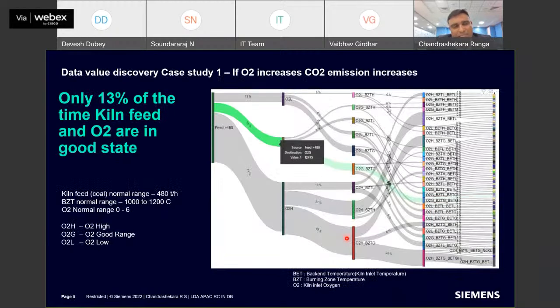When we did the case study, we noticed that only 13% of the time, both kiln feed and oxygen are in good condition. You can see this is called a Sankey plot, where on all other areas, only 13% of the time the industry is operating in very good condition. It may astonish many cement manufacturers: are we working at only 13% good condition? But looking at it another way, you have close to 80% opportunity to improve and perform better.